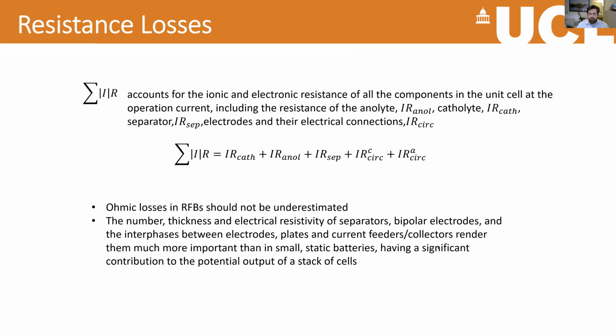There are also what's called IR potential losses. So this is just a simple sort of resistance, essentially, in our system. And using the equation V equals IR, we can figure out how much voltage loss we have based on the current density that we're at and the resistance within our system. So obviously there is electronic resistance in the system from the electrodes and all of the circuitry, but also there's quite a significant ionic resistance in the movement of the ions within the electrolyte. And particularly key is the movement of the ions between the separators. So the separator is a material that keeps the positive and the negative electrode apart, and the ions have to travel through that separator. And when they do so, there is a certain resistance associated with that.